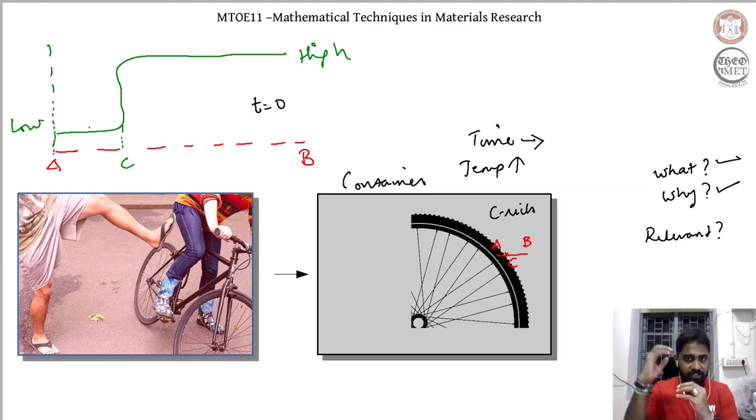So as I increase my temperature and hold my system at high temperature for a prolonged period of time, some amount of carbon moves from the carbon-rich surrounding to the carbon-deficit rim. Then after a given time t, in some region the carbon concentration decreases, and whatever amount of carbon is lost is gained by the rim.